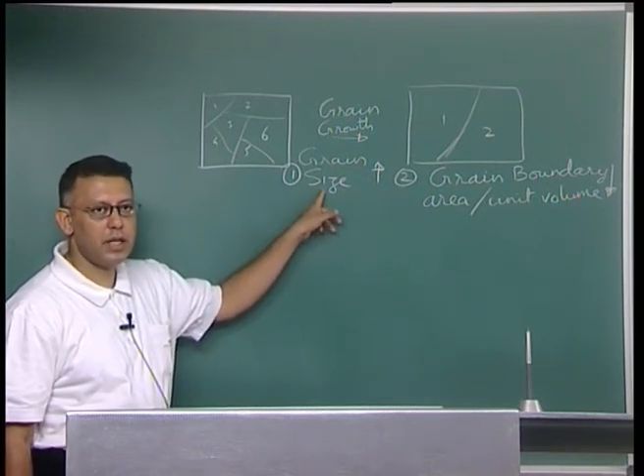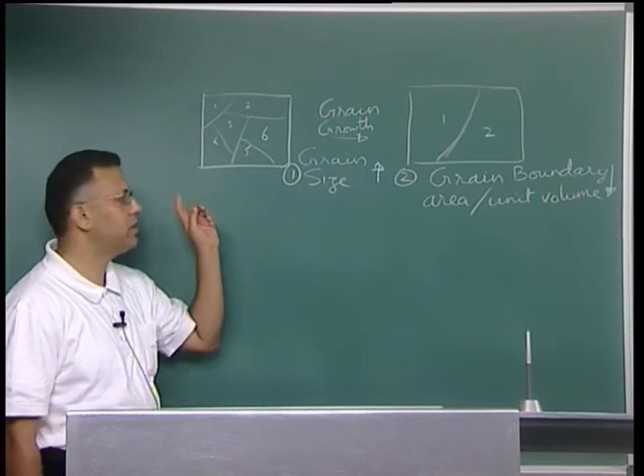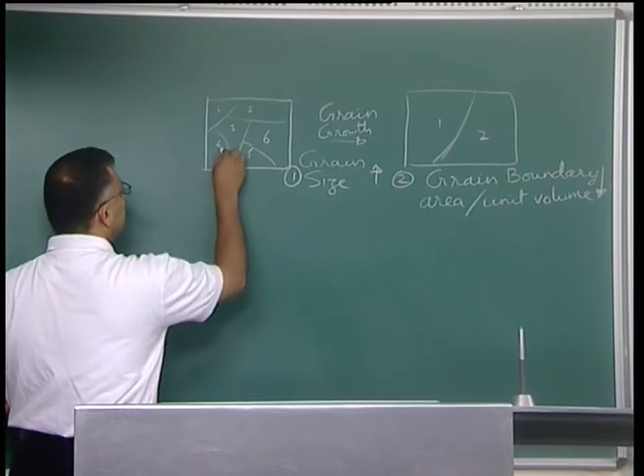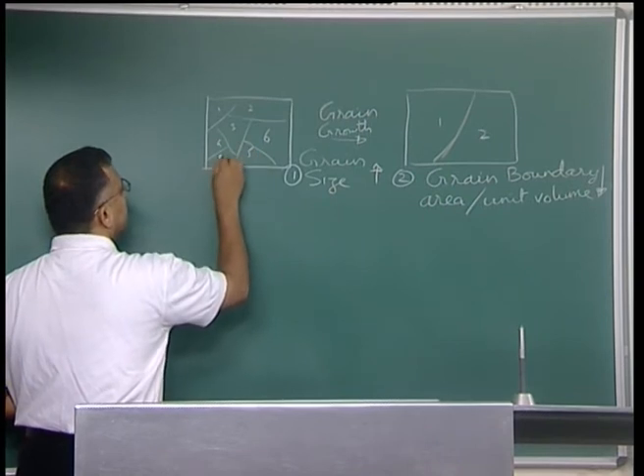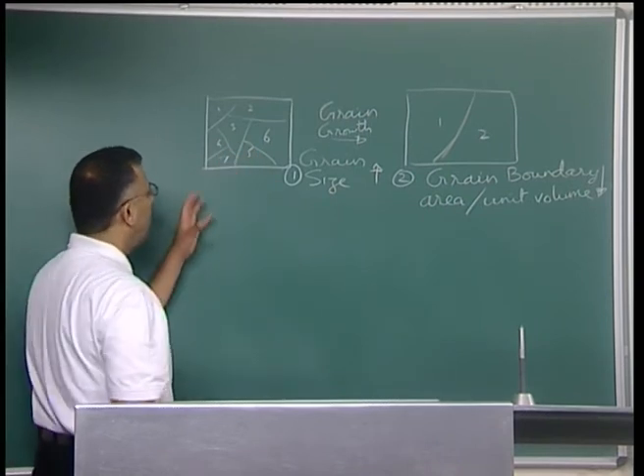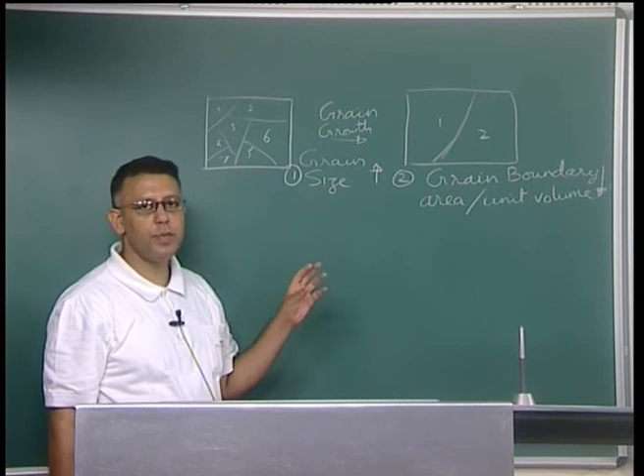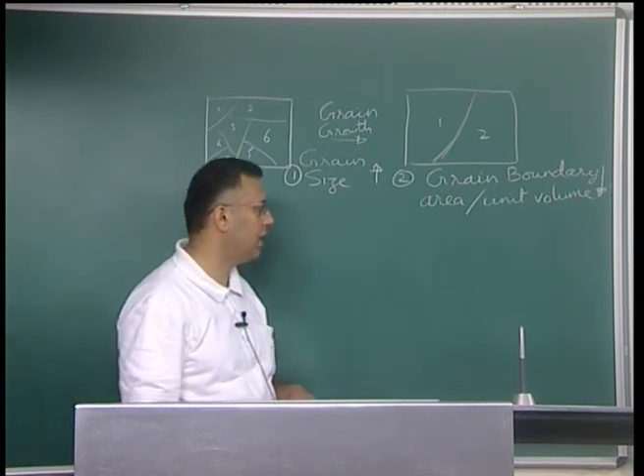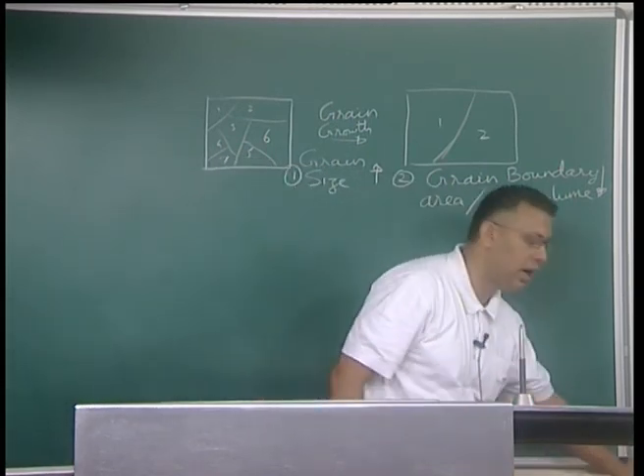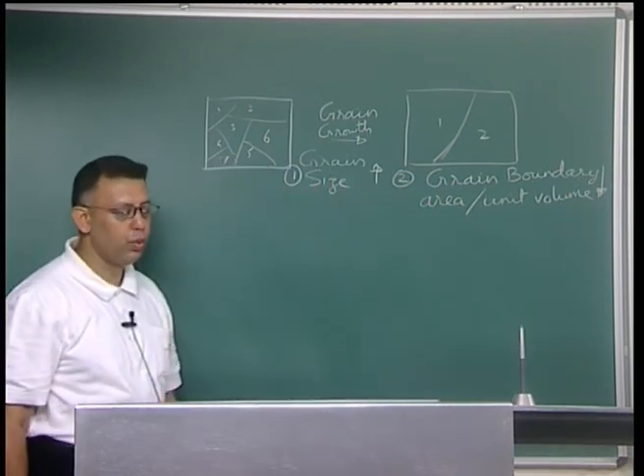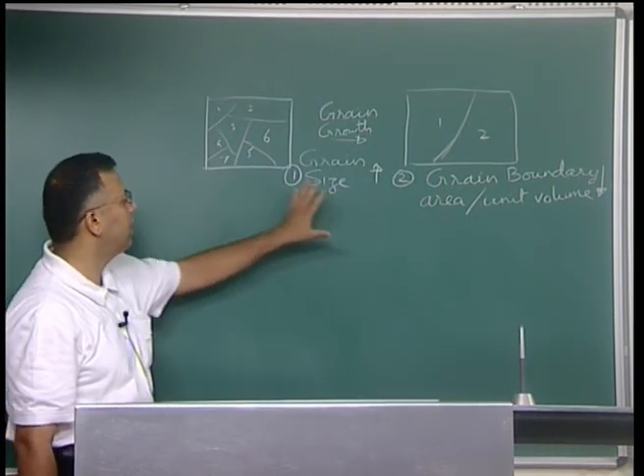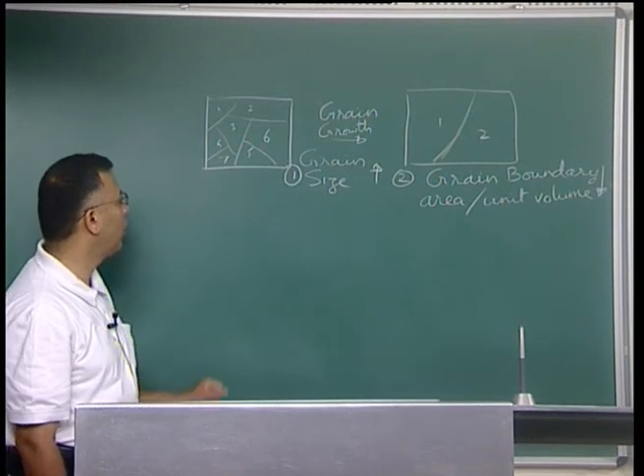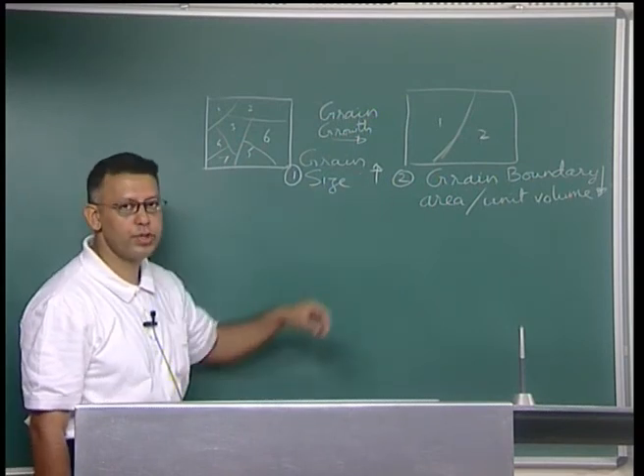Of course, grain size increase does not mean that each one of these grains is increasing. For instance, in a structure like this, there could be small grains like 7. This small grain may vanish, and this will typically happen at the expense of the larger grain. That means the smaller grains vanish at the expense of the larger grains. So, two important things I have to note. Overall, there is a reduction in interfacial energy as I grow from a fine grain material to a coarse grain material.